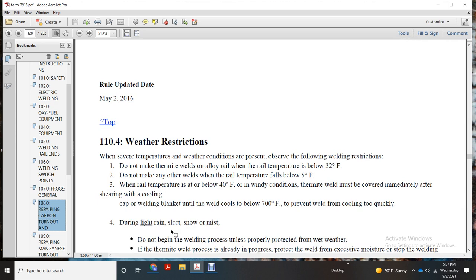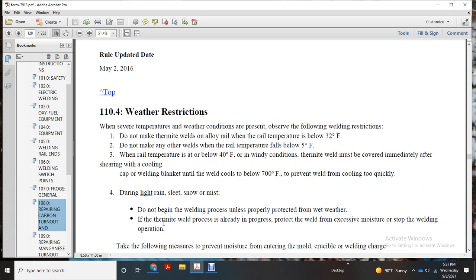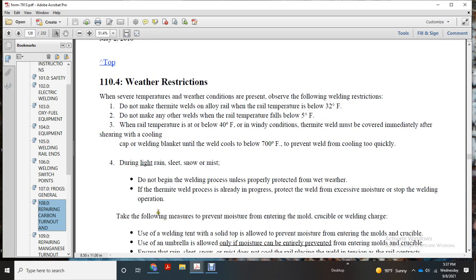When rail temperature is below 40 degrees Fahrenheit and wind conditions are present, the thermite weld must be covered immediately after shearing with a cooling end cap or welding blanket until the weld cools below 700 degrees, to prevent the weld from cooling too quickly. During light rain, sleet, snow or mist, do not begin the welding process unless properly protected for wet weather. If a thermite welding process is already in progress, take action to stop the moisture from disrupting the welding operation.